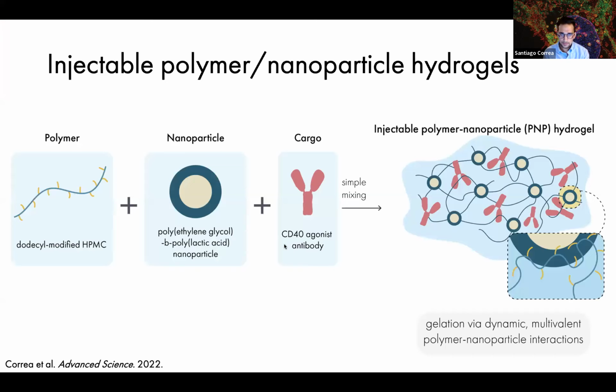And so here, the technology that we're using is a polymer nanoparticle hydrogel. This consists of a dodecyl-modified hydroxypropylmethylcellulose polymer and PEG-PLA nanoparticles. When you mix these two components together, you have spontaneous, non-specific interactions between the nanoparticles and the polymer that ultimately lead to this supramolecular hydrogel network forming. Because this happens spontaneously under mild conditions, we can incorporate sensitive cargo like antibody drugs simply by adding them into solution with the nanoparticles prior to mixing the two components together.